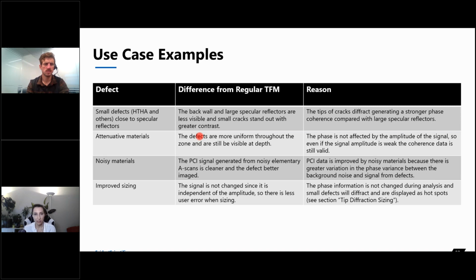But as I mentioned, for noisy materials as well, PCI signals generated from noisy elementary A-scan is cleaner and the defect better imaged. So as Trevor mentioned earlier, actually we need that noise to have very nice data. PCI does not perform very well on an extremely clean sample with a fake notch in it. We need those facets of the crack for the diffraction. We need that noise to compare what's coherent from what's not coherent. So again, noisy material is better for PCI. The data is improved by noisy material because there is a greater variation in the phase variance between the background noise and the signal from the defects.